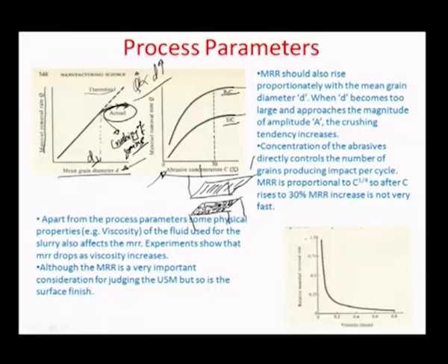accommodated. Okay. So even if the concentration is increased any further beyond that, you do not see much material removal, because the grains which are at probably the critical concentration here are fully packed into this area. So therefore there is a plateauing of the MRR with an increase in concentration beyond a certain critical concentration. So is the case with viscosity, a very important term for the slurry.